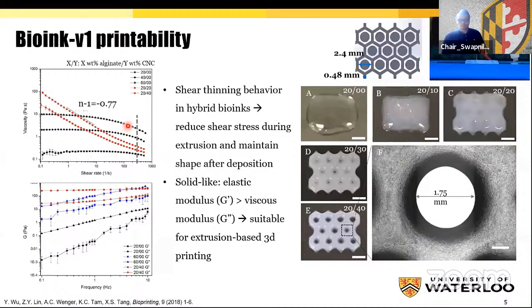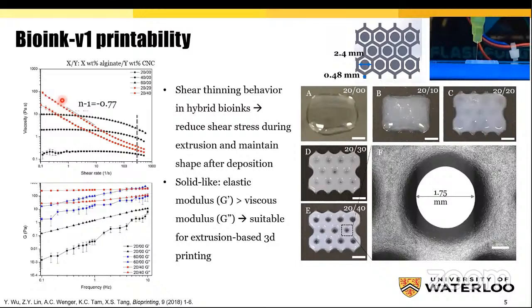Rheological tests were done on the bioink. We compared the pure alginate in black and the hybrid bioink in red and found significant differences between them. The hybrid bioinks exhibited strong shear thinning behaviors, which is contributed to the hydrogen bonding between alginate and CNCs. On the other hand, increasing alginate concentration from 2% to 6%, the viscosity increased over the whole shear rate range, but did not imply strong shear thinning behavior. With the same polymer concentration, their viscosity varies a lot at low shear rates. For instance, the viscosity of 6% alginate is constant at low shear rates, at a magnitude lower than the bioink 2040. So it suggests the hybrid solution enhances the printability and the fidelity.